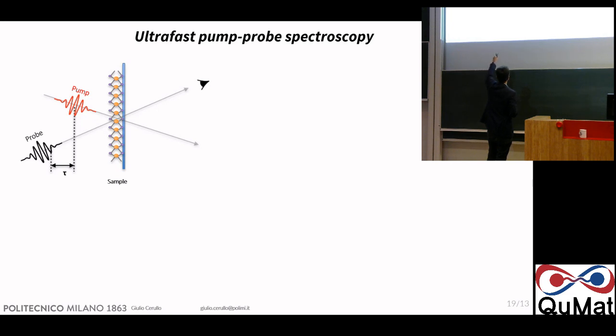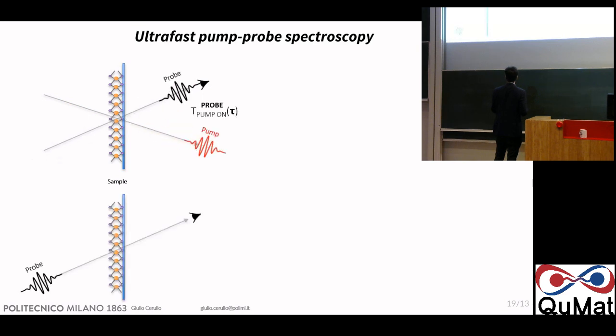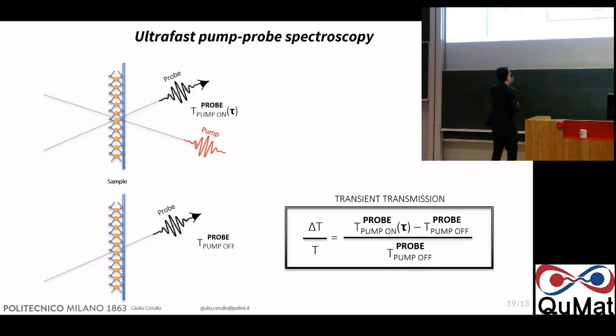So after the sample, you just measure your probe. And then you compare the transmission of the probe in the presence of the pump with the transmission of the probe in the absence of the pump. So you compare these two, and what you measure is the differential transmission: the transmission with the pump minus the transmission without the pump, as a function of the delay between the pump and the probe. And so with the pump, you modify the optical properties of the material.